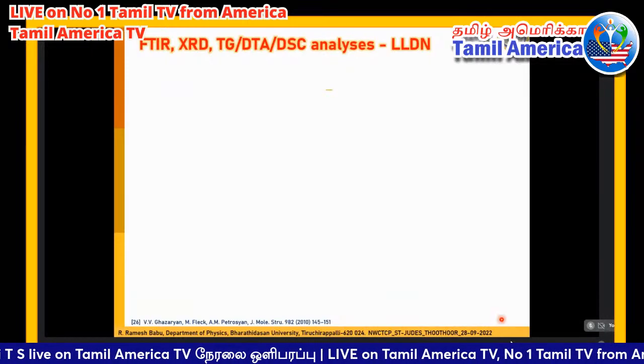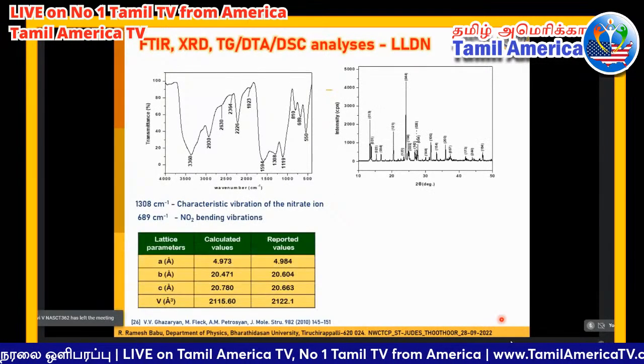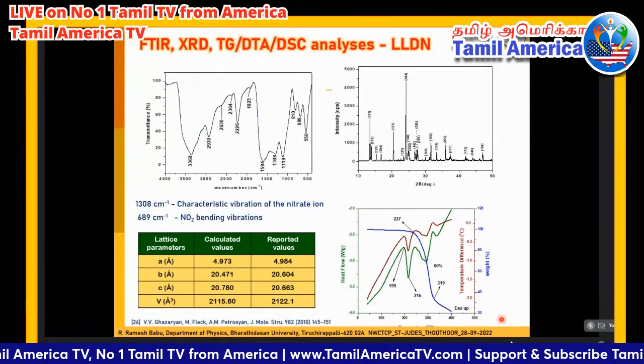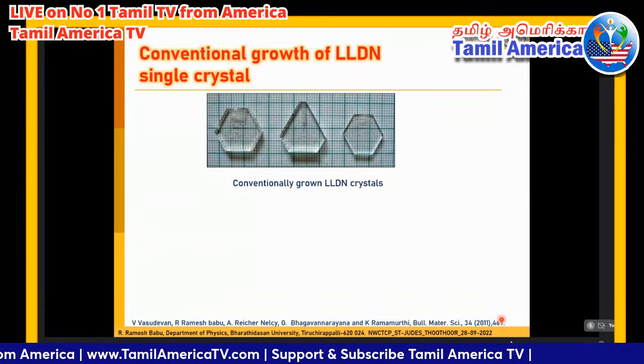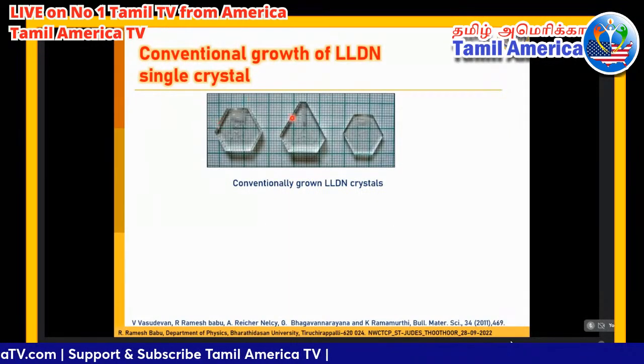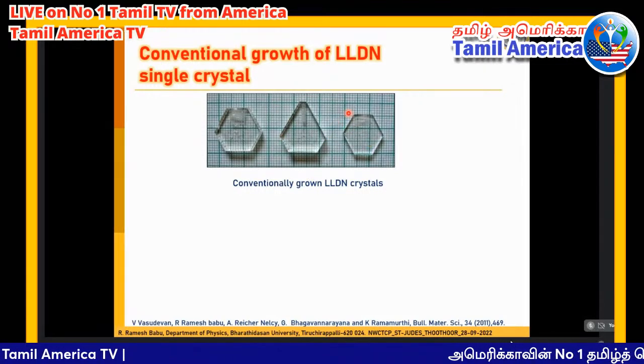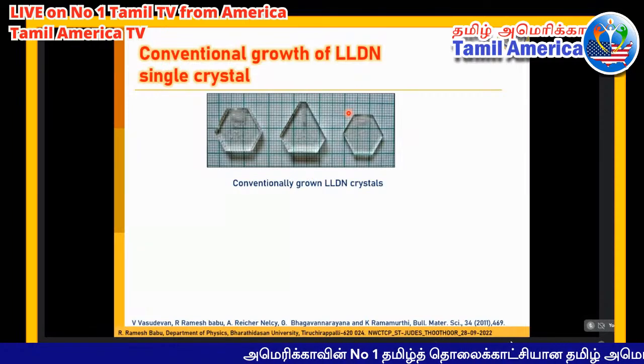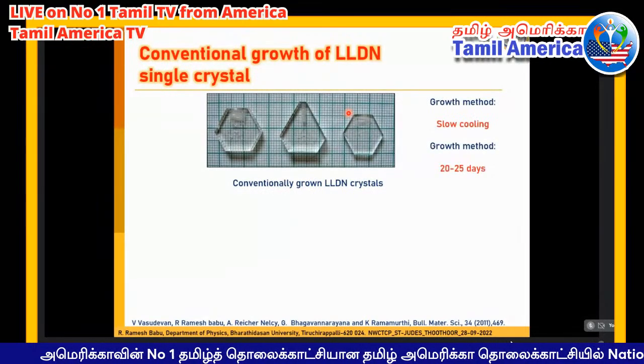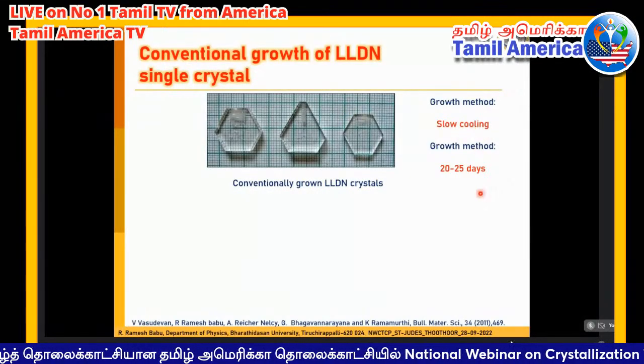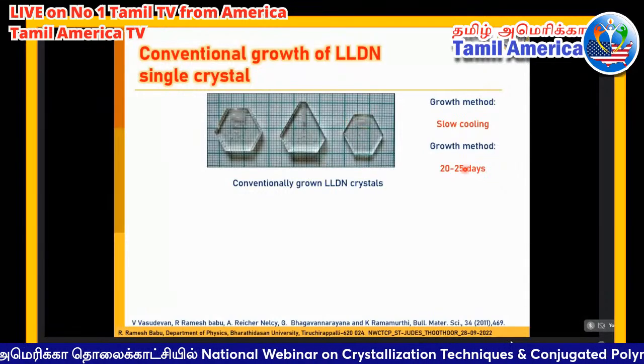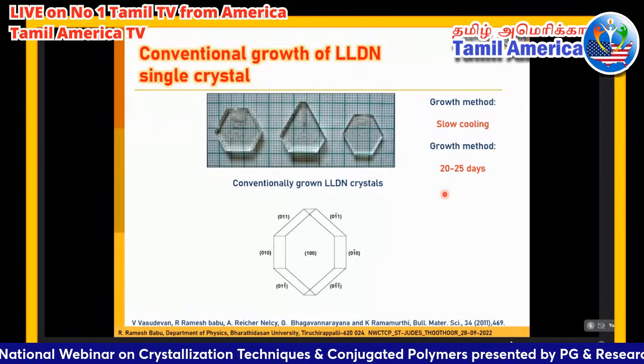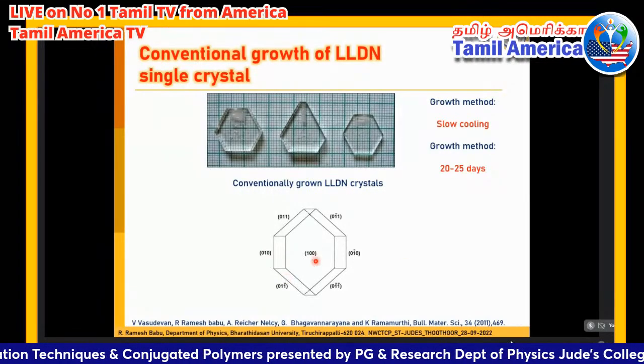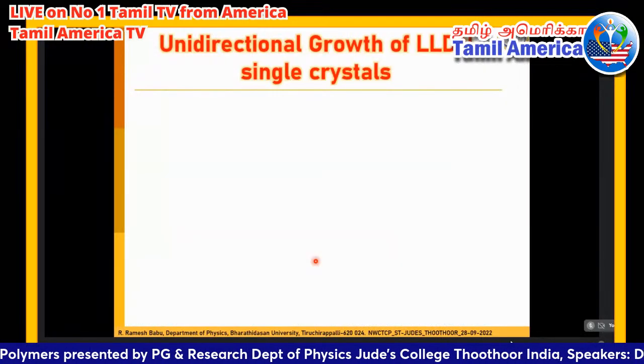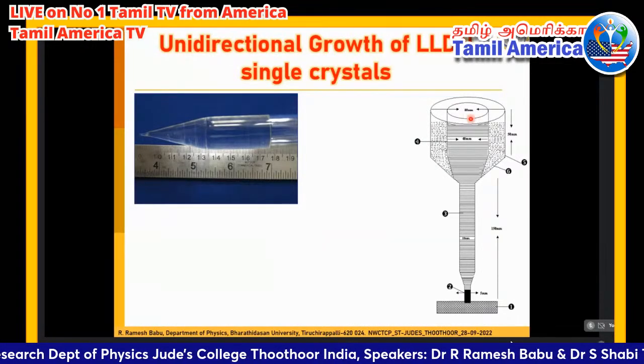After the preliminary investigation of the synthesized materials, like XRD, FTIR, and thermal properties, we subjected them to growth as bulk single crystals. This is the conventionally grown LLDN material. You see that it has a definite morphology and shape. Using this, we identify the specific direction to grow bulk single crystals for nonlinear optical applications. This is the slow cooling technique we employ to grow single crystals from the seed crystals. It takes 20 to 25 days. This is the morphology of the grown single crystals, from which we have identified the specific directions to grow bulk single crystals. The same, that is the crucibles we used.